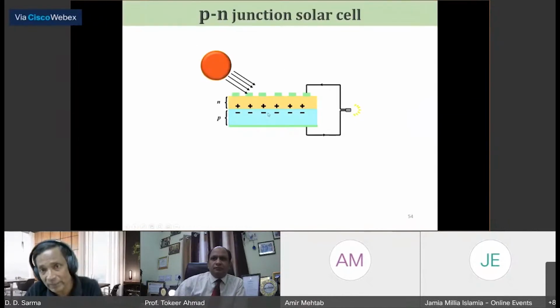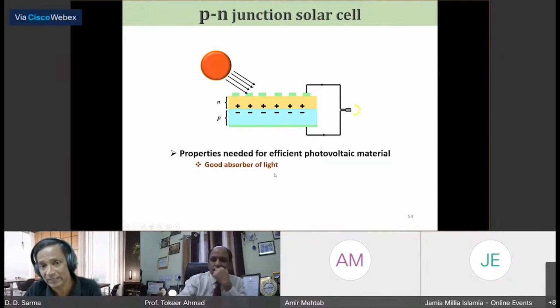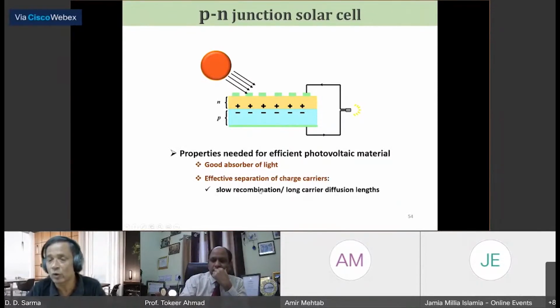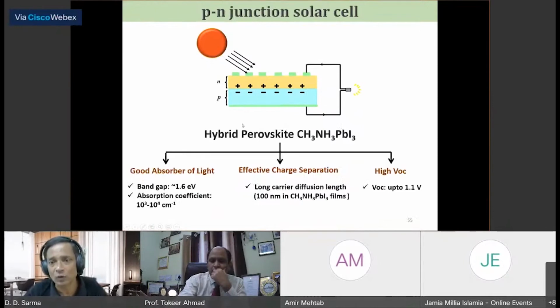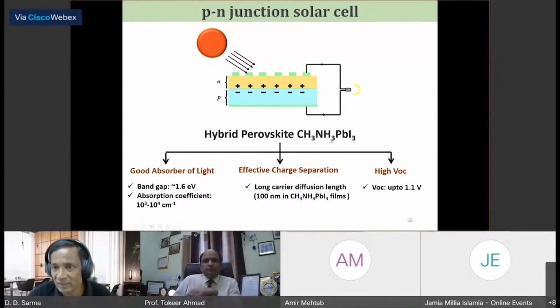As we know, what we need to make a good solar cell material is that it must have good absorption of light. It must give rise to slow recombination of the electron and hole that are generated, because if they recombine very quickly, then of course you won't get electricity outside, it gets recombined inside. And it must give rise to high voltage also, because the power that it generates is voltage multiplied by the current. And on all those counts, this particular family of materials, known as hybrid perovskites, does well, because it has an organic part, CH3NH3, methyl ammonium, and an inorganic part, lead halide, put in the perovskite structure.